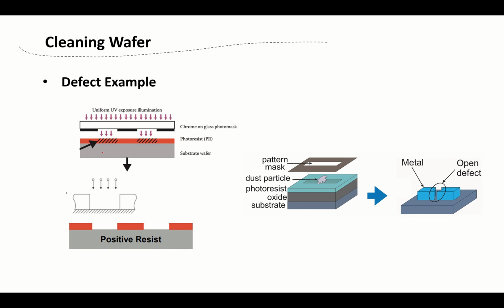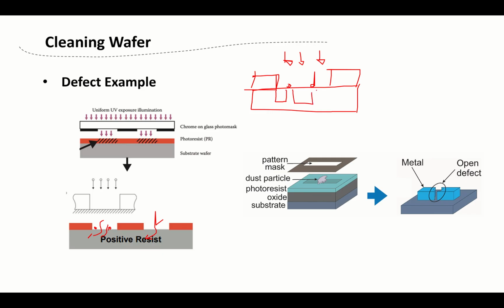Example. In here, we can see a lithography. After we do exposure, we do a developer to develop the PR. And if there are impurities here, as we can see, in the developer, mostly we will use TMAH to do that. If it includes some particles in the TMAH, probably here will be a particle, and here will be a particle. After you do etching, this part can be etched away, this part can, and this part can, but not this part. But originally, you want to etch the whole part, right? So here's the defect.